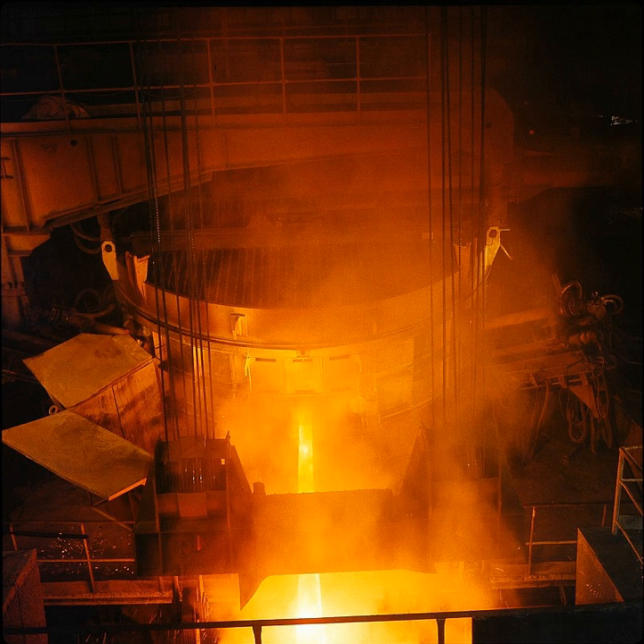Oxygen is blown into the scrap, combusting or cutting the steel, and extra chemical heat is provided by wall-mounted oxygen-fuel burners. Both processes accelerate scrap meltdown. Supersonic nozzles enable oxygen jets to penetrate foaming slag and reach the liquid bath. An important part of steelmaking is the formation of slag, which floats on the surface of the molten steel. Slag usually consists of metal oxides, and acts as a destination for oxidized impurities, as a thermal blanket, stopping excessive heat loss and helping to reduce erosion of the refractory lining.